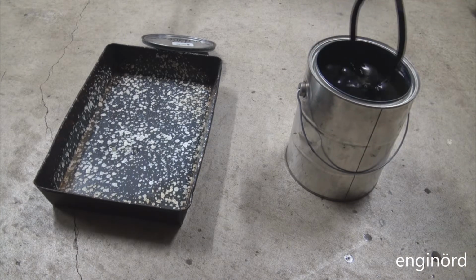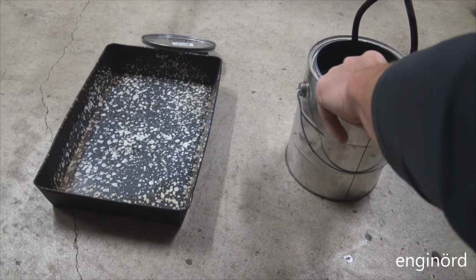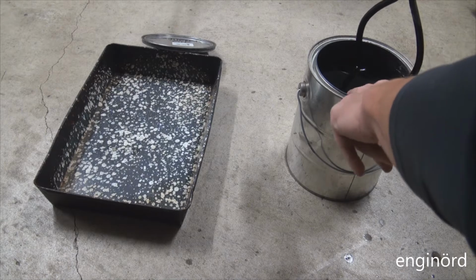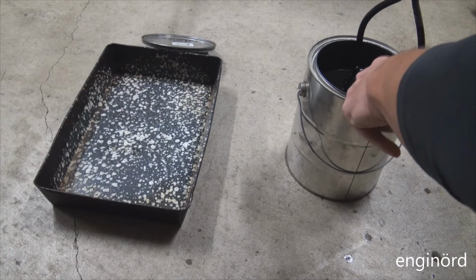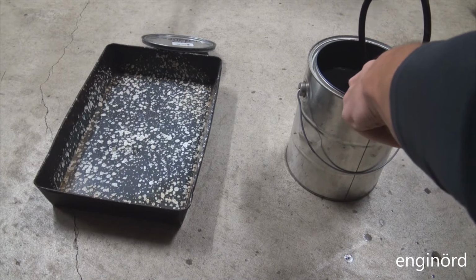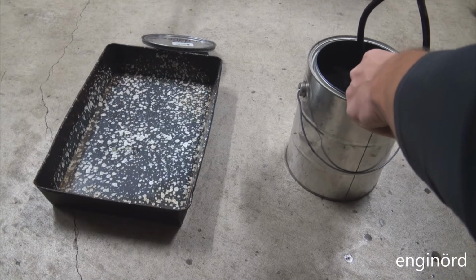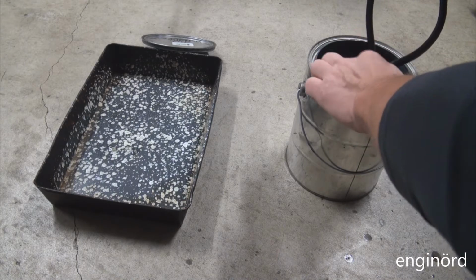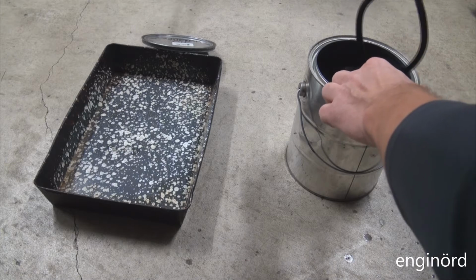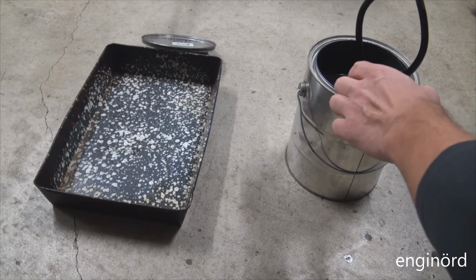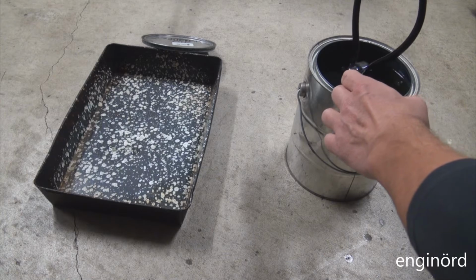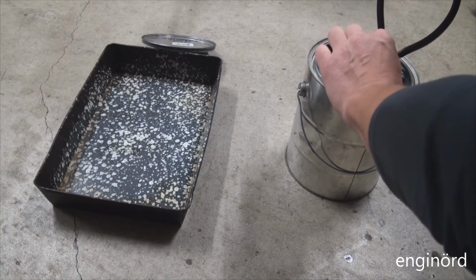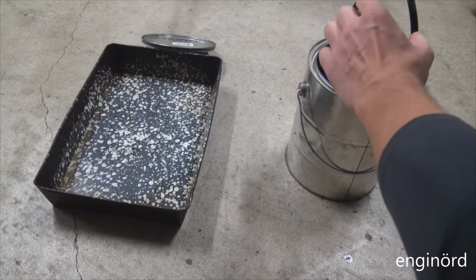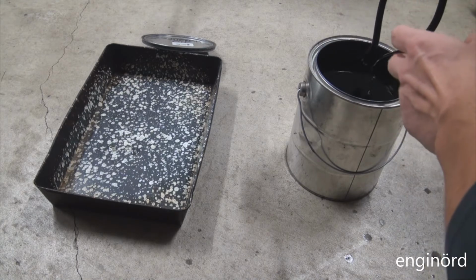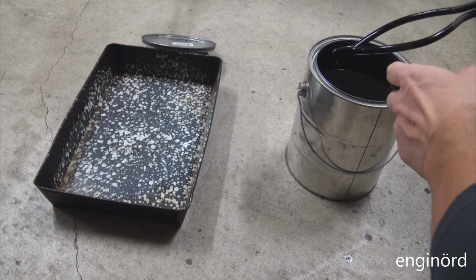The part is still pretty warm, so the oil did the trick, and the oil warmed up. I'd say it's about 30 degrees Celsius. It's nice and warm, but the part is still hot to touch. I can touch about 45 degrees centigrade. This is too hot to touch. So I'm just gonna let it soak there and cool down a little bit.